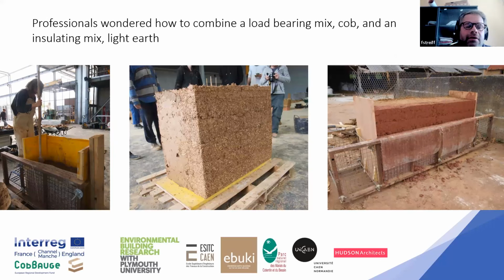So for that, as you've seen in the first study, we knew that just one mix was not the solution, but two mixes, one load-bearing, one insulating, were necessary. So we tried to experiment with builders. Here with Becky Little, builders from Scotland, during a training course near Lyon, we tried to produce a sample of a scale one wall, implementing those two mixes to see how it would react.